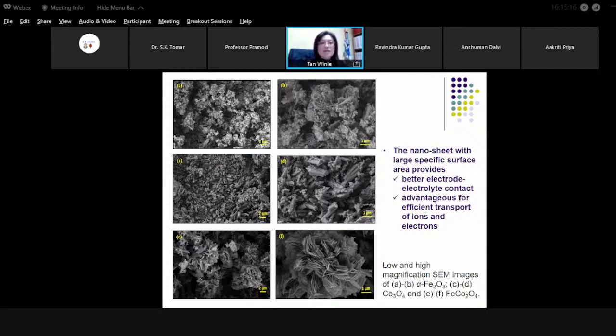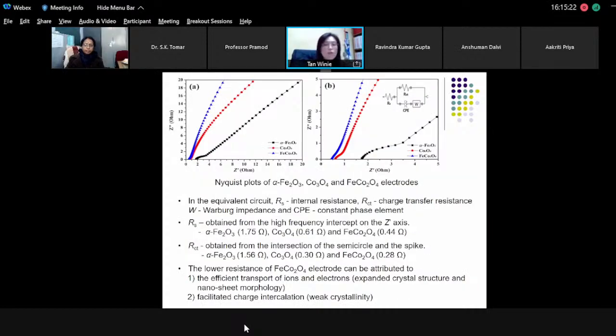Okay, so we did impedance, EIS. These are the impedance plots for these three materials. You can see the occurrence of the semicircle at the high frequency region by magnifying these figures in the right figure. This is the magnified figure of figure A. Here is their equivalent circuit representation. RS is the internal resistance, RCT is the charge transfer resistance, CPE is the constant phase element, and W is the Warburg impedance.